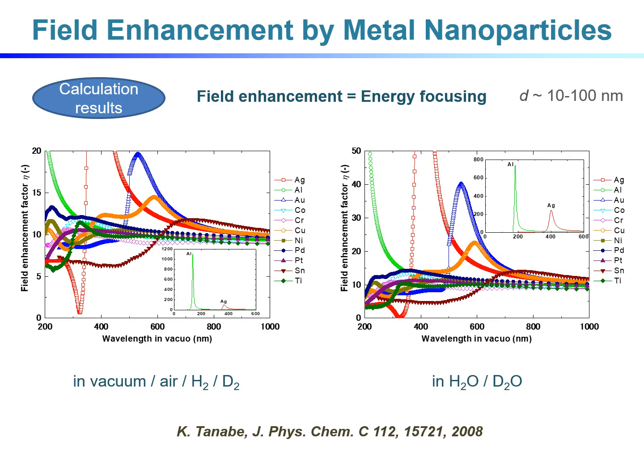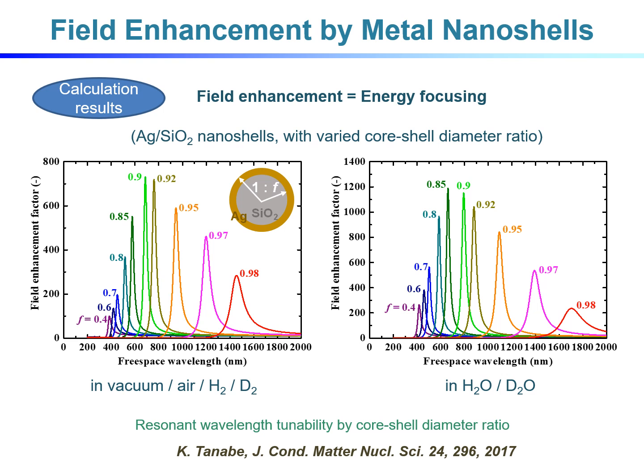These are the calculation results for the field enhancement factors for spherical metal nanoparticles in deuterium and heavy water. Aluminum, silver, and gold show distinctively high enhancements because of their high electric conductivities. Palladium, nickel, and titanium show enhancement factors of about 10 in this optical frequency regime. For metal nanoshells, the field enhancement effect becomes much stronger. For example, silver-silica spherical nanoshells show peak enhancement factors as large as 1000, and we can tune the resonant wavelength or frequency by the core-shell diameter ratio.